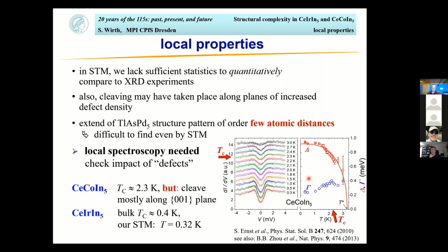Now, of course, if you want to do a comparison between STM and XRD, you would like to do that on a quantitative basis. But we cannot do that. We lack sufficient statistics in the STM. We saw these patterns every once in a while, but I don't dare to give a number on how much of the surface we saw with this additional structural pattern. Also, I should say, we did a cleave, so we only look at the surface. So that might actually also influence what we are looking at. What we can say is that this additional structure pattern is only a few atomic sizes in size. So it's actually difficult to find in STM. You really always have to zoom in.